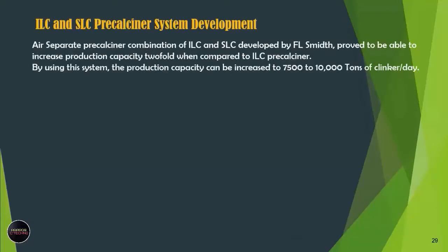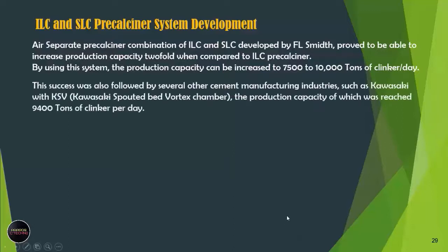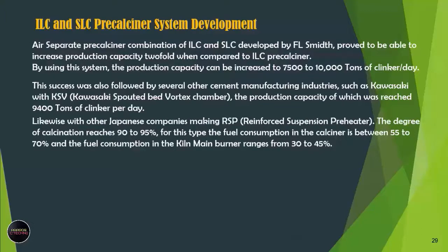Development of ILC and SLC precalciner systems. The air-separate precalciner combination of ILC and SLC developed by FL Smidth proved to be able to increase production capacity twofold when compared to the ILC precalciner. By using this system, the production capacity can be increased to 7,500 to 10,000 tons of clinker per day. This success was also followed by several other cement manufacturing industries, such as Kawasaki with KSV, Kawasaki spouted bed vortex chamber, whose production capacity reached 9,400 tons of clinker per day.